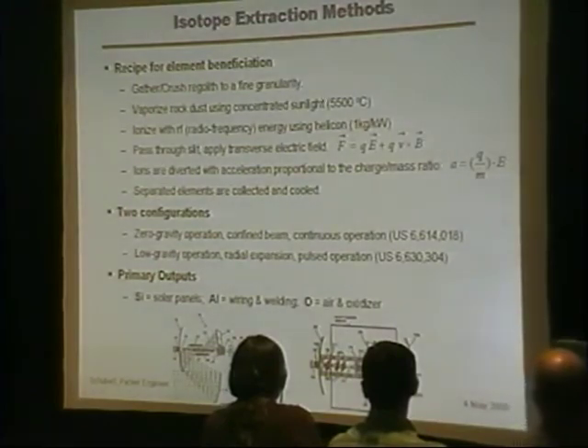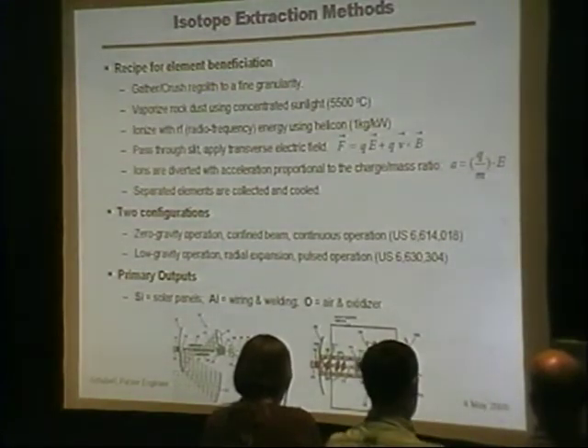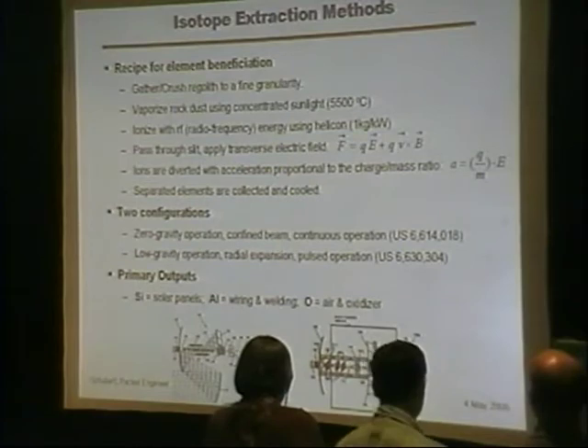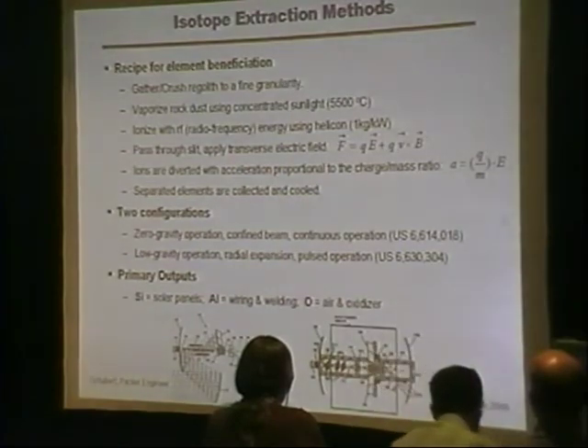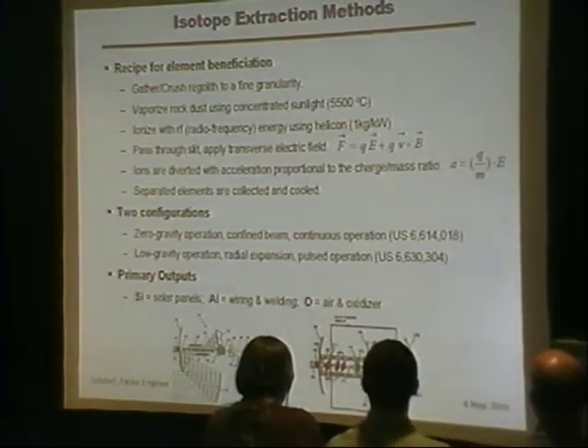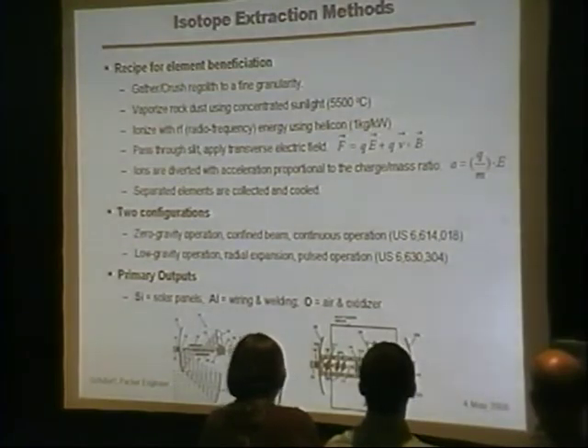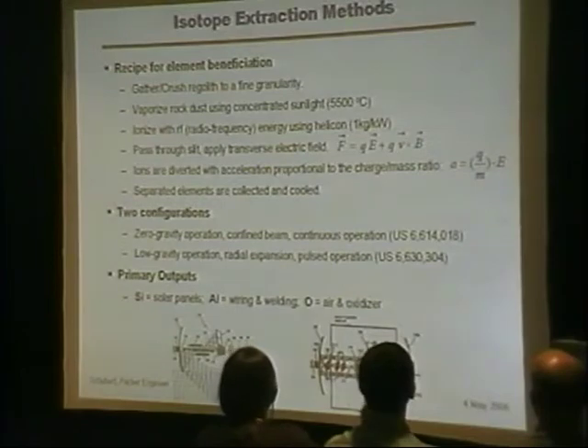Mass spectroscopy is a technique that's being used for analyzing samples. It's a very commonly used technique. These 2 inventions are based on a large-scale mass spectroscopy where you first crush or sieve the regolith to a fine granularity, vaporize it with concentrated sunlight. The surface of the sun is about 5,500 degrees centigrade, so that's the highest temperature you can get for that. But that'll vaporize just about anything. Then you can ionize this with radio frequency energy using helicon sources, pass these through a slit, and apply a